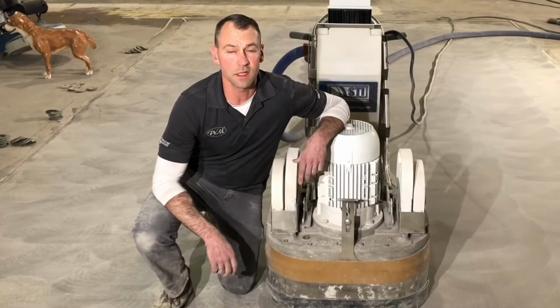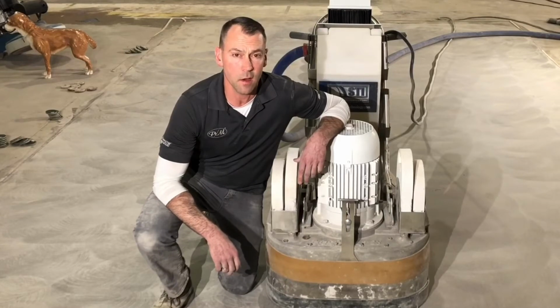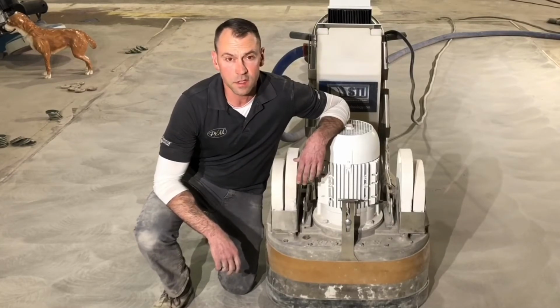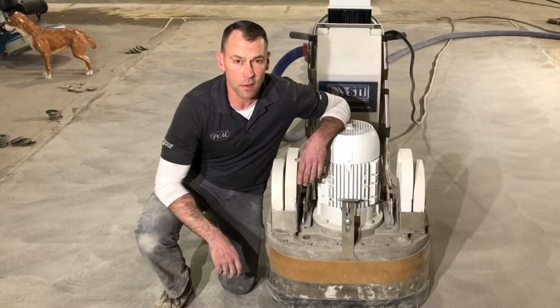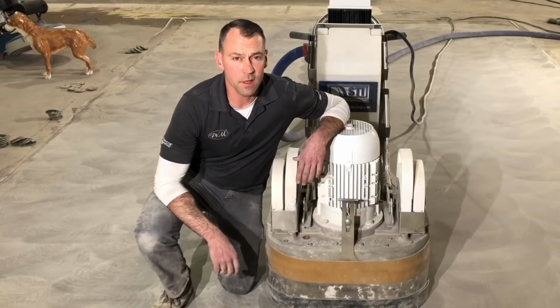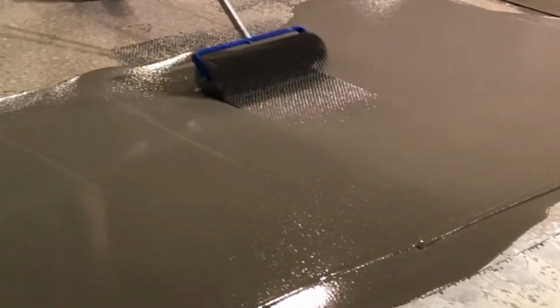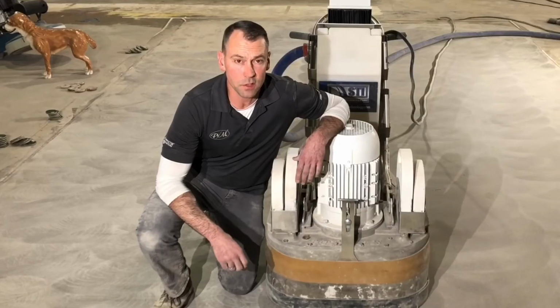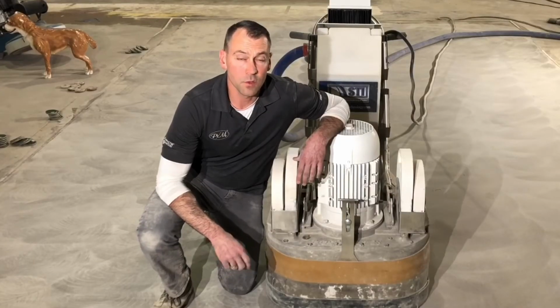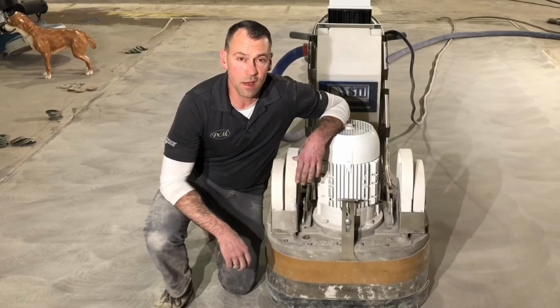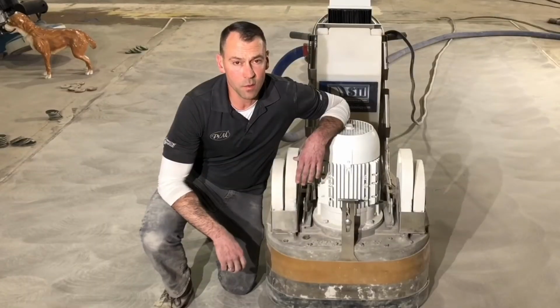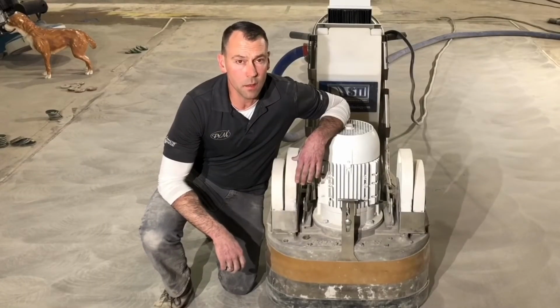Also, because we tested a smoother to smooth the material out, and also a spike roller to see how that would affect the finish, we found that from the spike roller, there were actually marks in the surface that gave it almost a carpet look or a loop look. What we think happened is the spikes pushed the aggregate down and allowed the matrix, or the material itself, to come up. Because of the weight of the aggregate, once it's pushed down, it doesn't necessarily want to come back up to the surface. So we end up with a patterning on the surface of the floor that would probably not be acceptable because again, when it's polished, it's only going to become more noticeable.